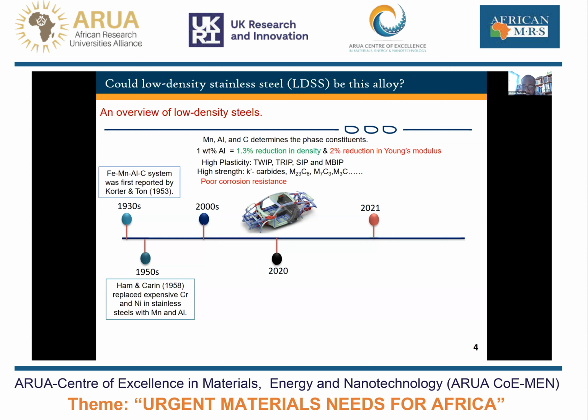And that was when we really developed the metallurgy of low density steels. The key alloying elements are manganese, aluminum, and carbon. When you introduce manganese, you reduce the density of the alloys as well as the elastic modulus. But more important is aluminum, because it has very low density. So when you add aluminum to iron, you reduce the density quite a lot.